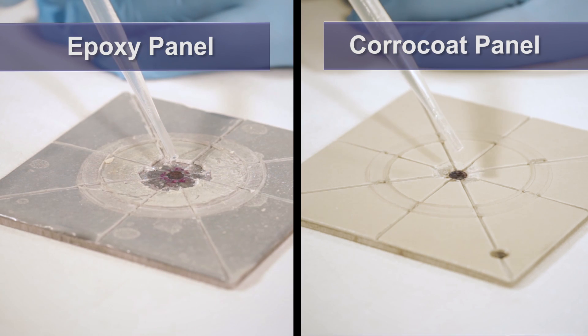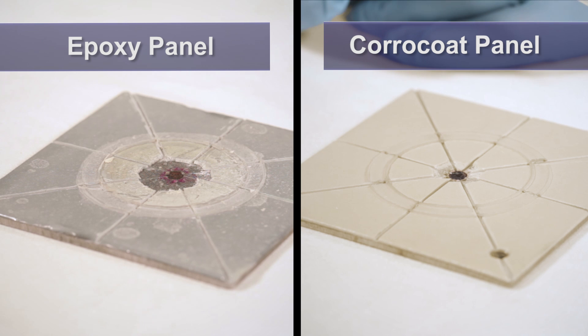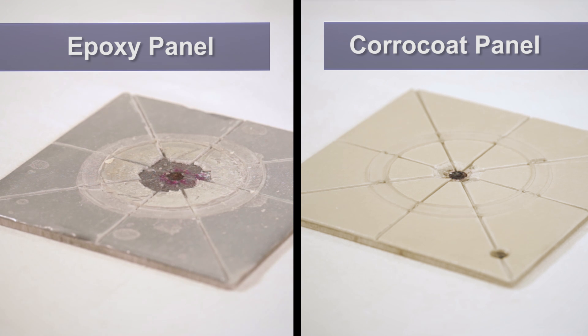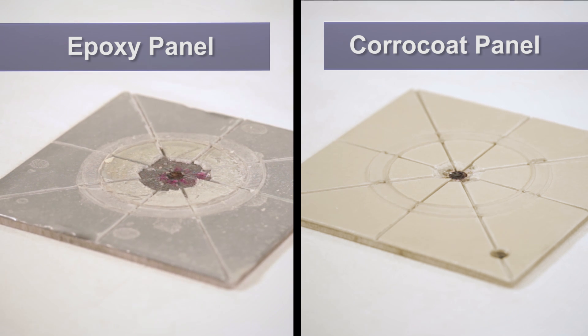The Corrocoat glass flake coating, cut with a hacksaw, has a high resistance to moisture vapour transmission, high electrical resistivity and high adhesion value and, as a consequence, excellent resistance to cathodic disbondment. This type of coating is a rigid material and is often difficult to determine where the disbondment is due to mechanical chipping and where the disbondment has occurred solely due to the cathode effect.